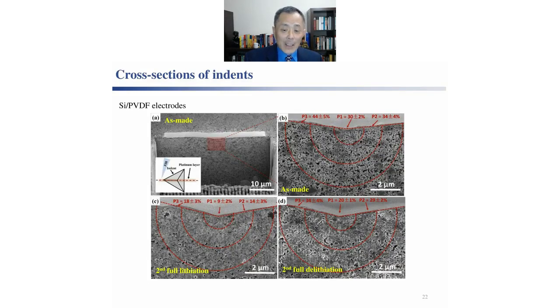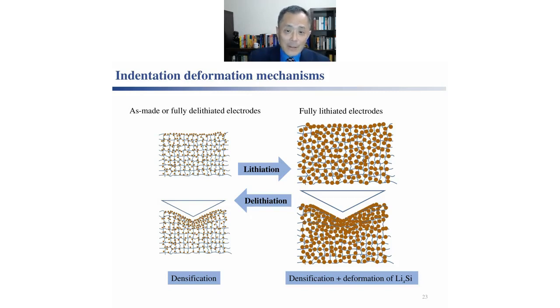And that can be verified by these cross-section images of the electrode under the indent. The electrode, freshly made electrode, under full lithiation and under full delithiation. And as these images show, the porosity indeed changes as a function of lithium content. The images also help us understand the deformation mechanisms. When the porosity is high, the deformation is mainly caused by the deformation of the binders and the densification under the indent.